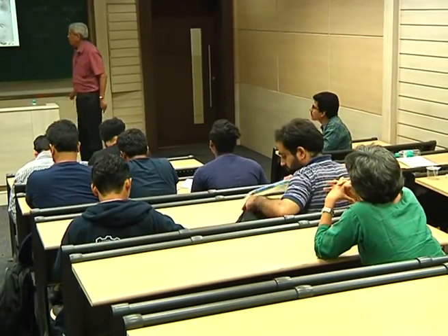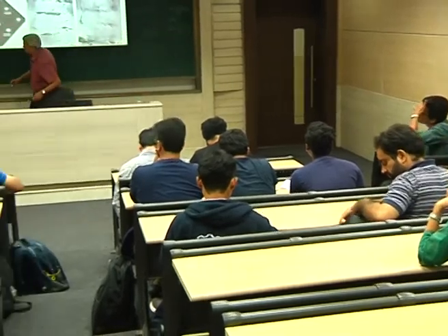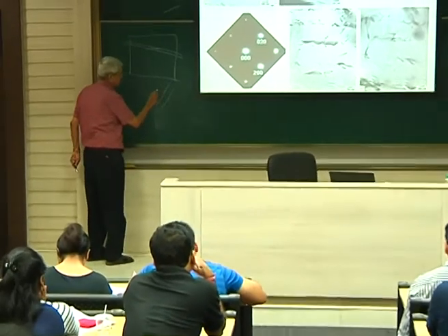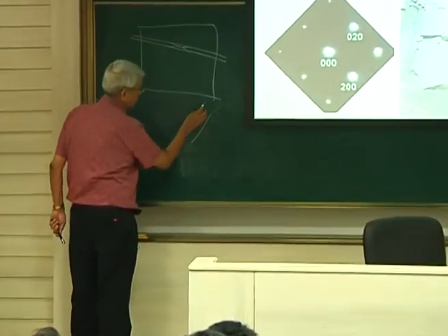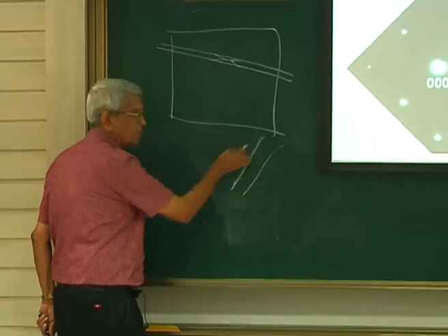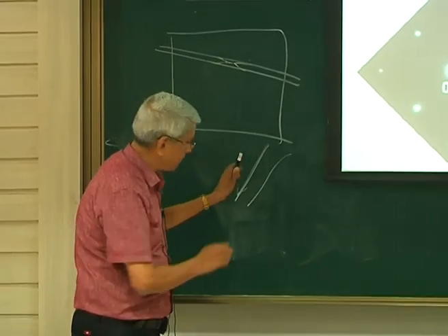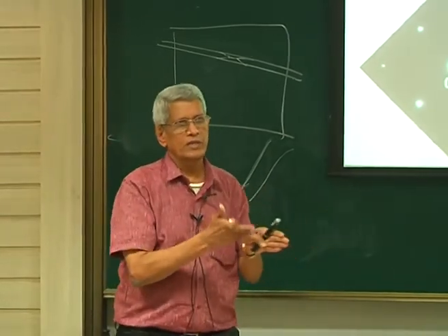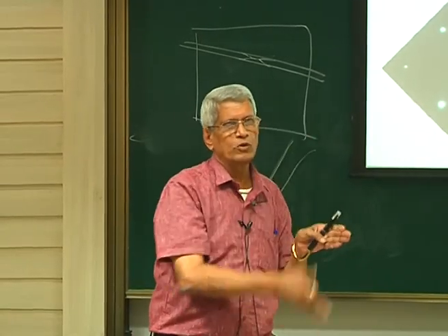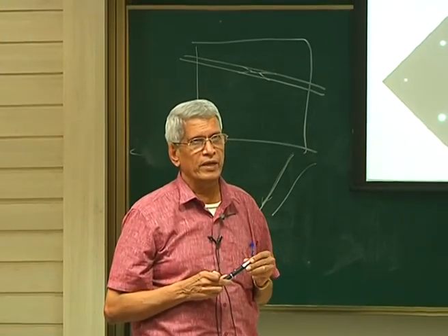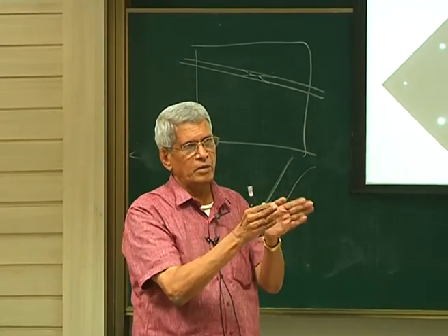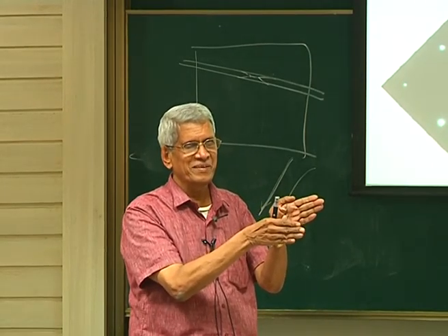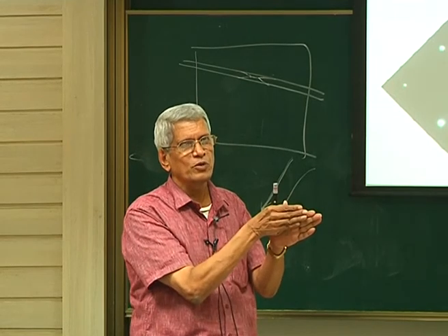Yes, they can be done. What essentially has to be done is that in such cases, suppose the dislocations are there like this, and if I tilt the sample along the dislocation line, taking that as the axis of rotation, we can make the plane containing these two dislocations parallel to the beam direction. If they are on two parallel planes, then you will find that still these two dislocations will be two different ones. Otherwise, they will be merging together into one.